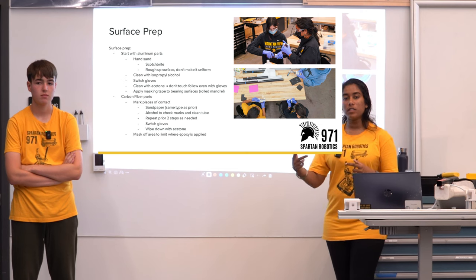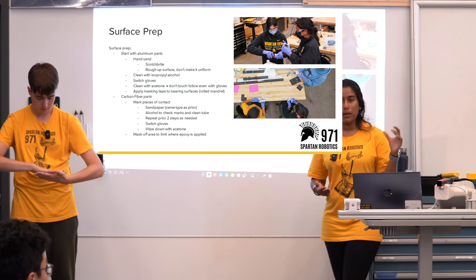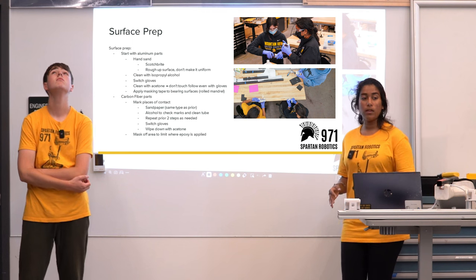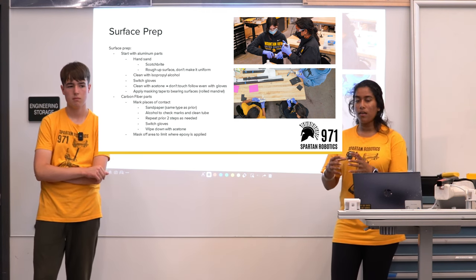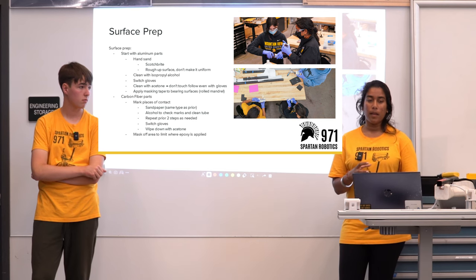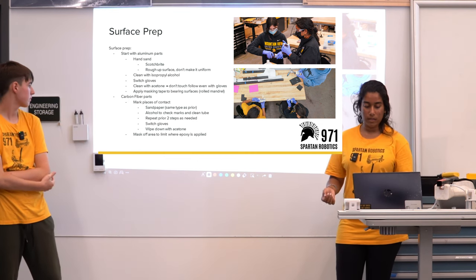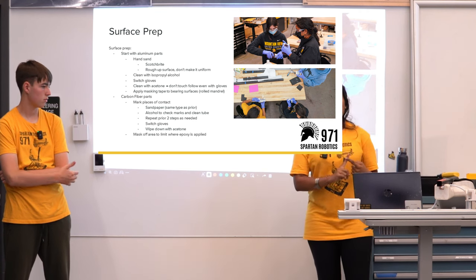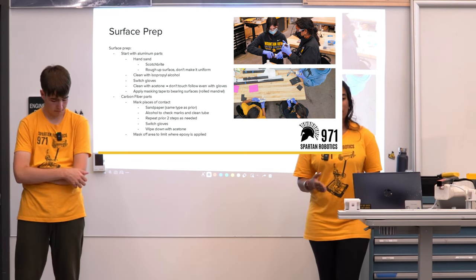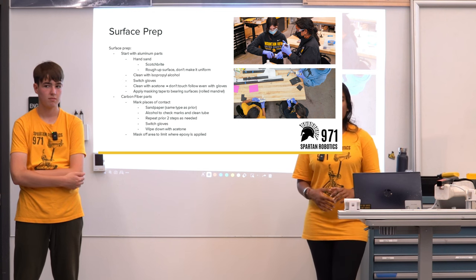Repeat these steps until you have a matte finish. Then switch your gloves and wipe down with acetone as well. Also mask off any area you don't want epoxy — this is really important for bearings, since any epoxy on a bearing surface will prevent the bearing from fitting. On 3D printed parts, be careful: acetone can melt them, so we used only isopropyl alcohol to clean those.